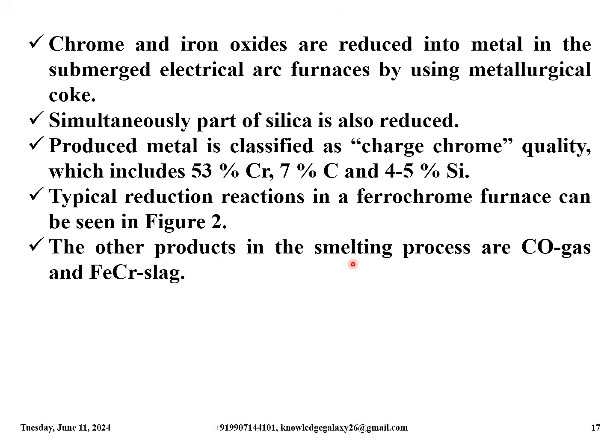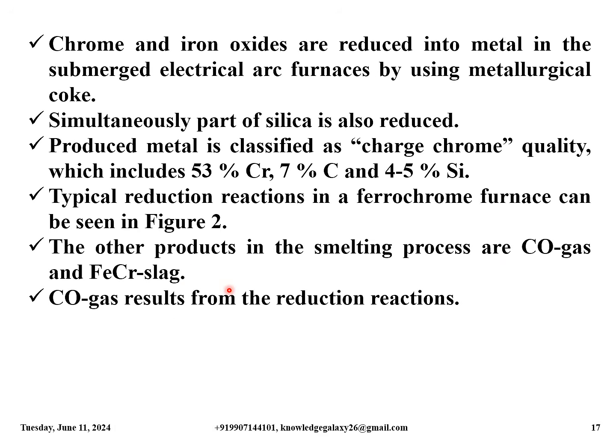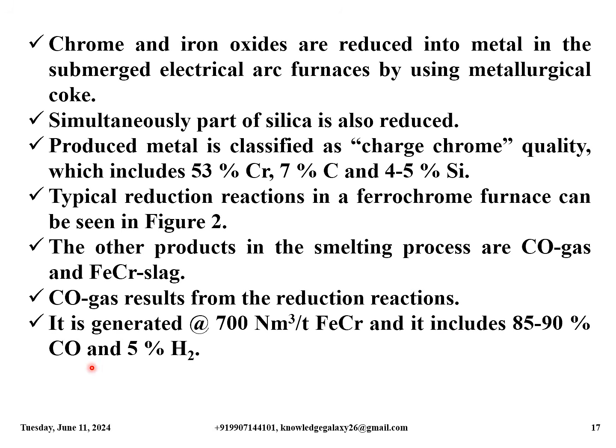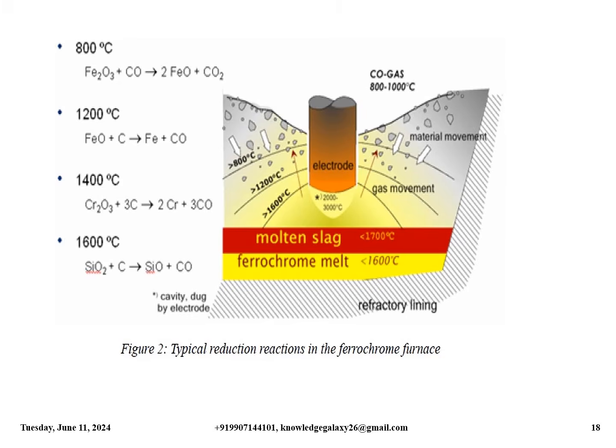The other products in the smelting process are CO gas and ferrochrome slag. CO gas results from the reduction reactions. It is generated at the rate of 700 normal cubic meters per ton of ferrochrome produced, and it includes 85 to 90% CO, that is carbon monoxide, and 5% hydrogen. These are the typical reduction reactions occurring in the ferrochrome furnace. You can pause the video and observe the different nomenclatures and reactions in the ferrochrome production process in different layers.